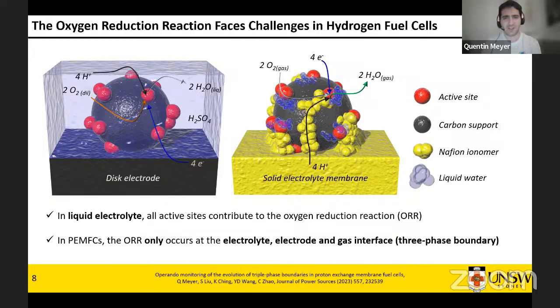What you need for the reaction to happen is oxygen, electrons, and protons at the same place at the same time. This is called the triple phase boundary, which is the way the reaction happens. It's at the electrolyte, electrode, and gas interface. Depending on how well you design your fuel cell and your electrodes, you may have only 10% of your active sites, the materials in red, or 80% of the active sites producing reactions. It's quite a challenge to have as many active sites as you want.